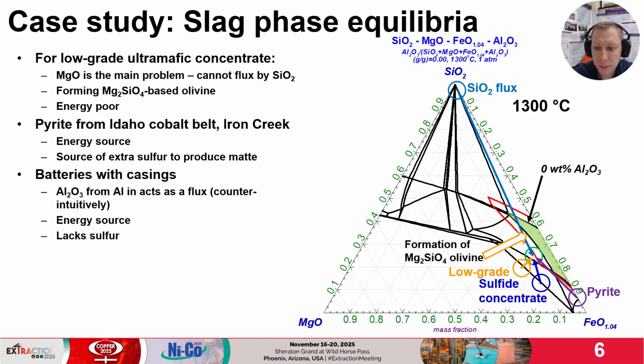We also have batteries. They don't have much MgO, SiO2 or FeO, but they do have aluminium, which is converted into aluminium oxide. Typically, Al2O3 is considered a problem, hard to flux, but in this case, the solid phase of concern is olivine, and the presence of Al2O3 in the slag increases the solubility of MgO. Batteries provide energy but lack the sulfur to form matte. Thus, pyrite is also complementary for lithium-ion battery recycling. The converter slag comes back and it is already fluxed with low MgO concentration.